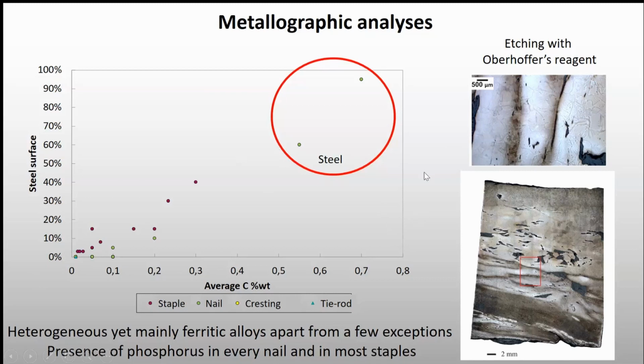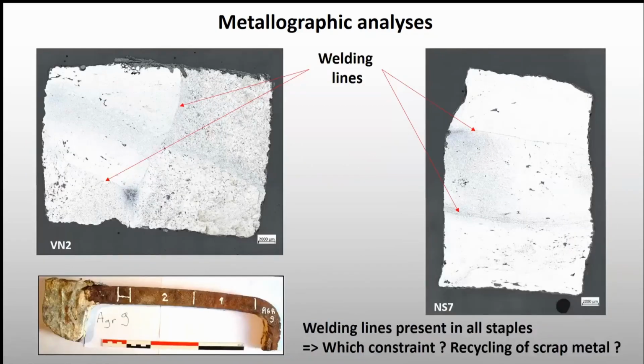We did not make some micro hardness tests on Notre-Dame, but we did it on other buildings before, and that's what it actually showed. So there's a lot of phosphorus in many nails and in most staples actually, and also for the 19th century elements. One feature that was interesting, and that we did not expect, is that in the staples they were systematically welding lines inside their matrix.